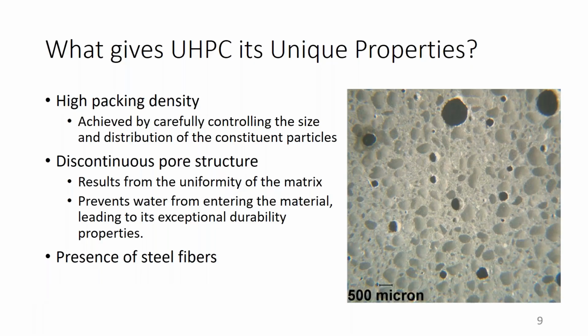So why is it such a unique material with unique properties? Well, it's because of the high packing density. The sands in the material, there are 2 of them. They fit such that one of the small particles of the fine sand fit in between some of the larger sand particles. In between that fit the cement particles. In between that fit the silica fume particles. This packing density is quite high, much higher than regular concrete.